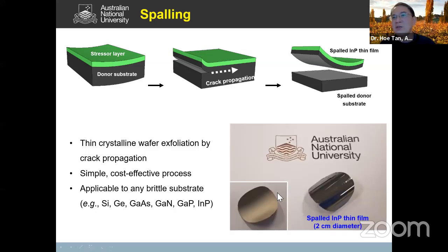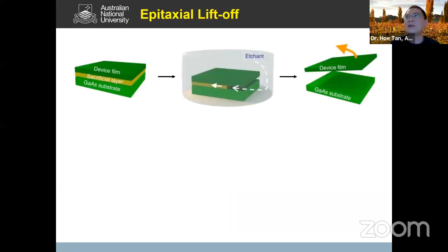And shown here, see, we spall off a thin indium phosphide layer, which is a wafer scale. This is about 2 centimeters, but since then, we've got something a bit bigger now. So another flexible device fabrication technique that we are developing is this epitaxial lift-off layer.